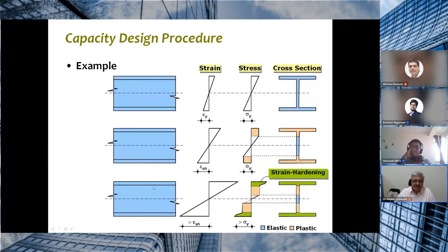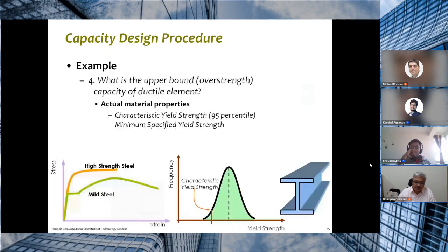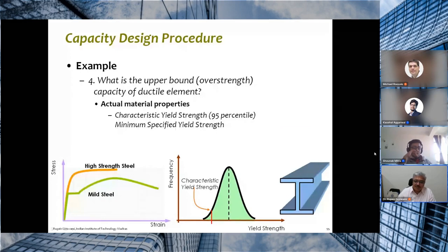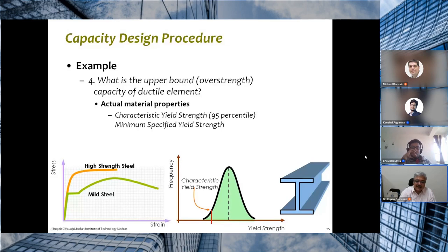Essentially, what happens in beams with doubly symmetric I sections is that the flanges go into strain hardening, and that gives the additional strength. But more importantly, the strength that we use in our design calculation is the nominal or characteristic value, which means in most cases that value is going to be exceeded. For instance, if we are looking for steel with 250 MPa yield strength, in most probable cases the actual yield strength will be more than 250. And there is nothing much to be unhappy about it.